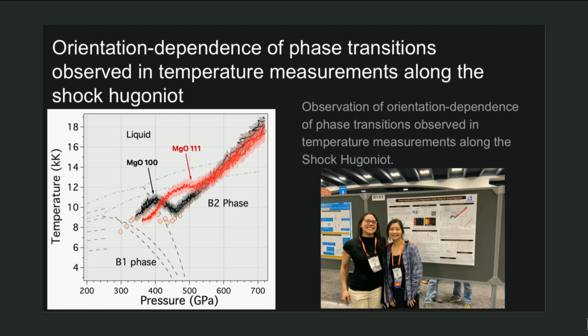What was really surprising also is that if we look at this material and shock along a different orientation, we get a different answer in temperature. And so we have sensitivity to orientation dependent effects. And so this is potentially a way for us to really explore the atomic motion and the non-hydrostatic environment as the shock wave is propagating. And so looking at how we can access potentially different structural transitions, by looking at both the temperature and the X-ray diffraction measurements, allows us to potentially answer this question.